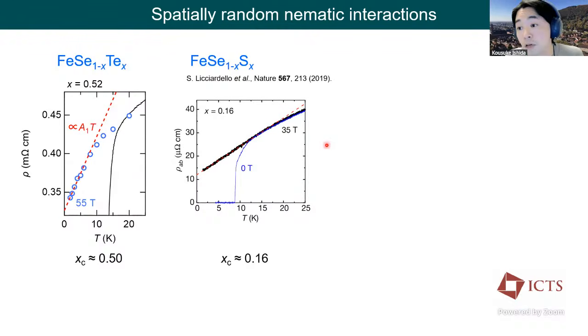And one possibility I want to argue here is substitution-induced disorder. Okay, this is almost the last slide. The amount of substitution at the QCP in iron selenium telluride is larger than in iron selenium sulfide. This leads to a residual resistivity one order of magnitude larger than iron selenium sulfide. So this motivates us to consider a model of fermions coupled to substitution-induced spatial random nematic interactions.